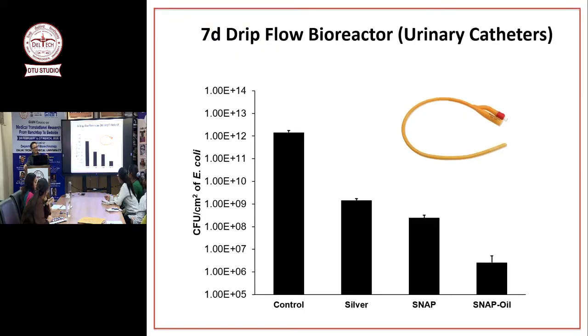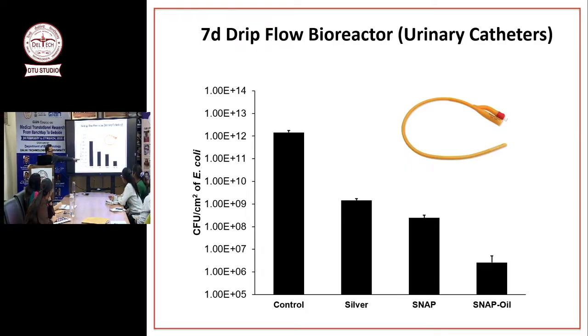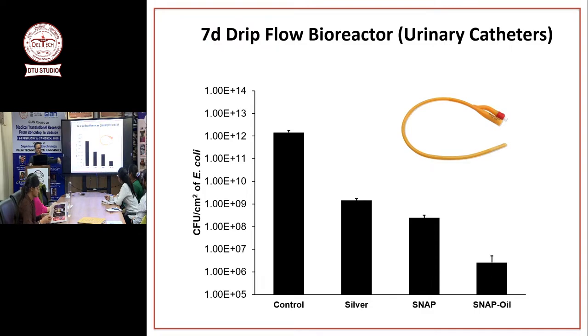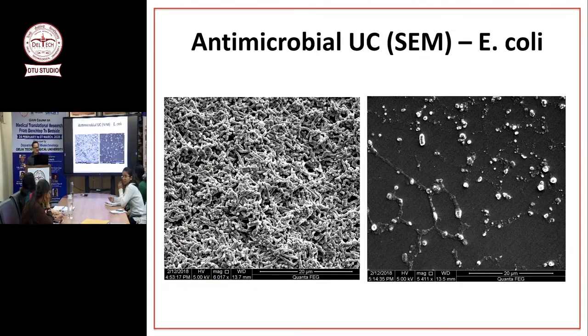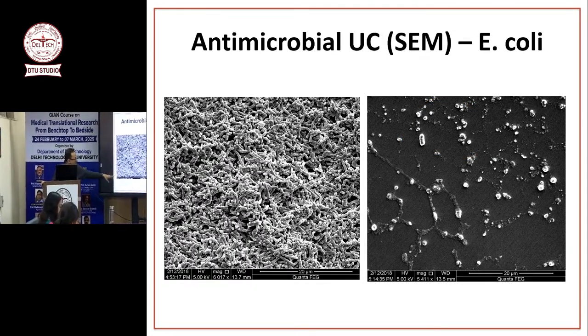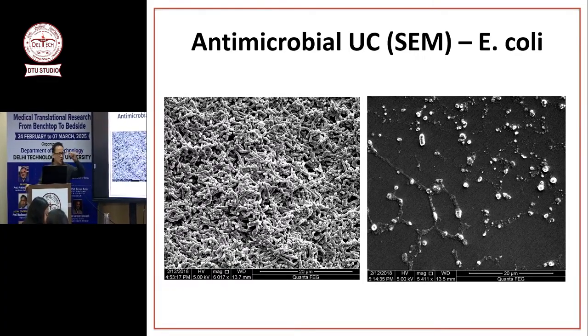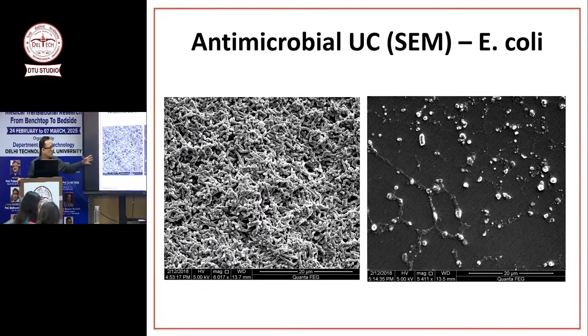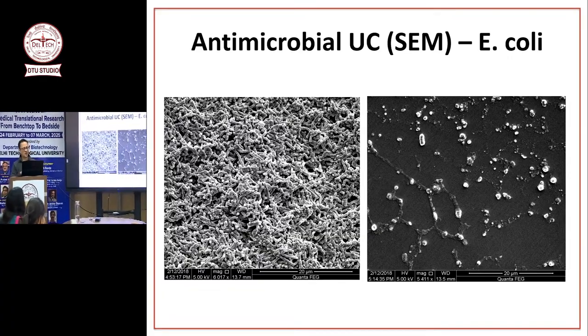When we did a 7-day bioreactor study, we saw that our catheter was almost 2-3 log reduction better than only silver or only SNAP. The combination was better than anything else. We also looked under SEM, and you can see all this is E. coli. They are rod shaped, and our slippery surface was almost totally clean.